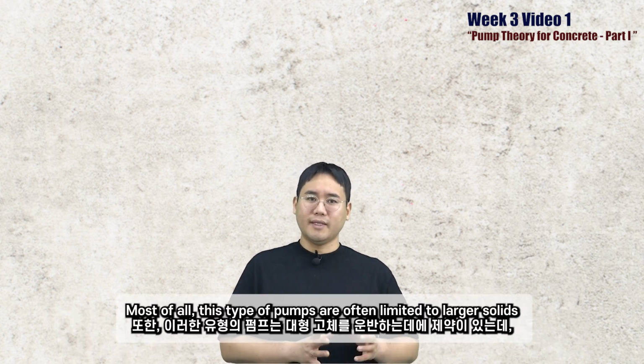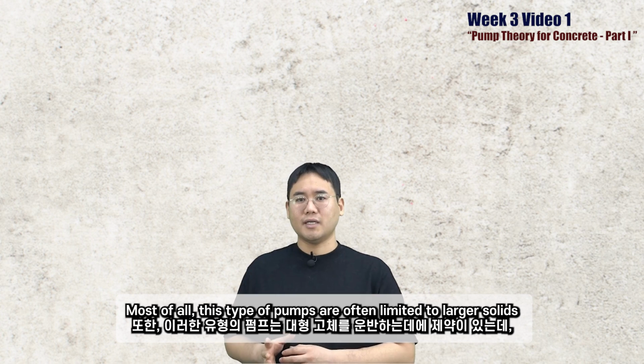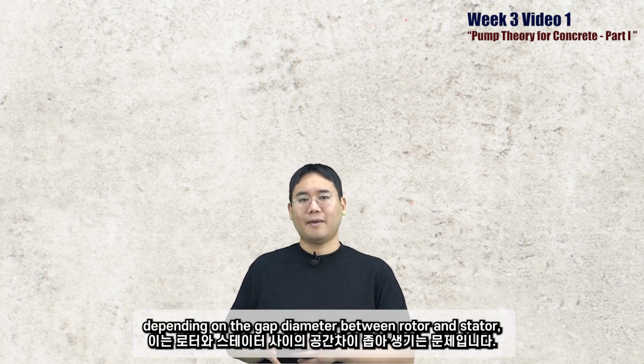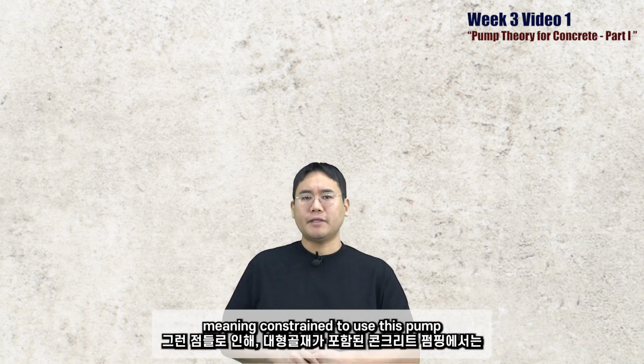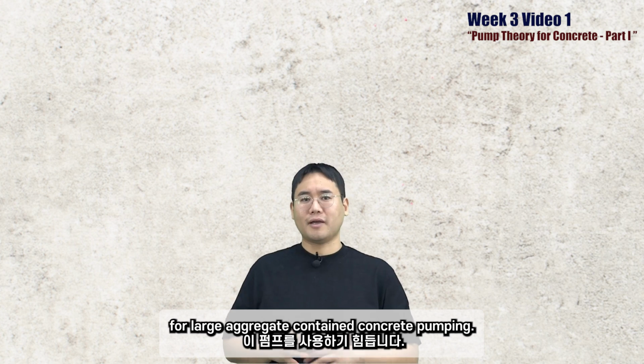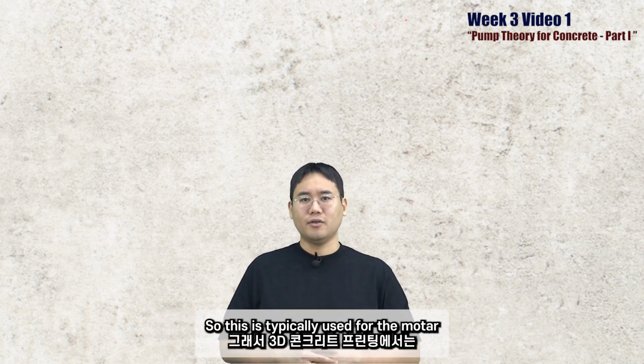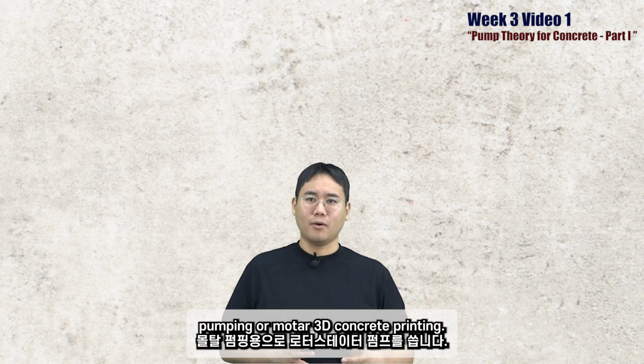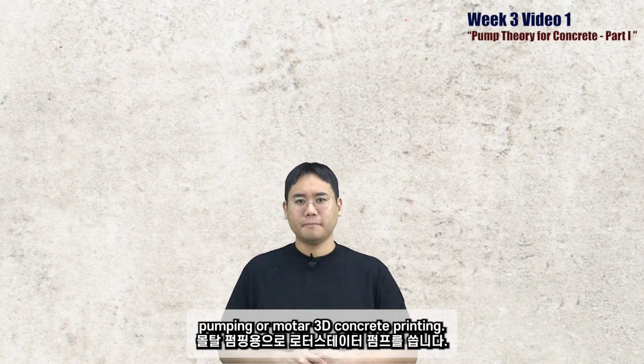Most of all, this type of pump is often limited in the solid size it can handle, depending on the gap between the rotor and stator, basically the specification of the rotor and the stator, meaning we are constrained from using these pumps for concrete containing large aggregate. So this is typically used for mortar pumping, or mortar 3D concrete printing.